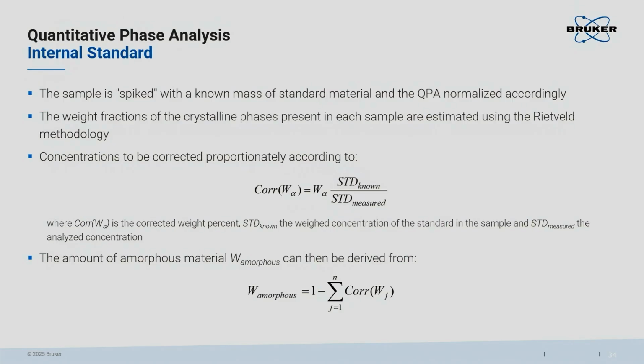Internal standard method, here you spike the sample. People do not like to spike their samples. Why would you? You are contaminating your sample. It is a lot of efforts. If you have a lot of samples to spike, this is also not funny. However, it puts the results of the Rietveld method on an absolute base. So if you need absolute results, spiking is one way of doing it.